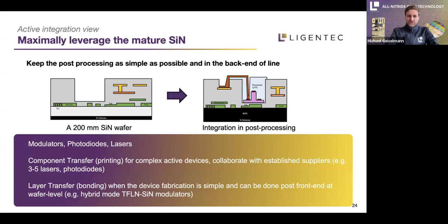And so we take a 200 millimeter silicon nitride wafer with all the standard modules that you see here. So here a standard module, as I mentioned before, is a cladding opening where you remove the oxide and you get access to the evanescent field of the silicon nitride here below, and then you can integrate heterogeneously other materials to it.